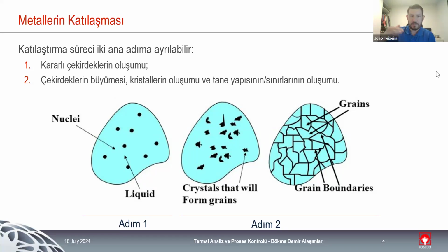And as time goes on and we lose temperature, we lose heat inside either the ladle or the mold, these nuclei start to grow. They start to go against one another, and they start to solidify in what we call a cast iron part, the component that we are producing. So basically, the first step is the formation of stable nuclei, growth, and the formation of grain boundaries when all these grains start to go against one another. This is a simple explanation of how cast iron alloys solidify.